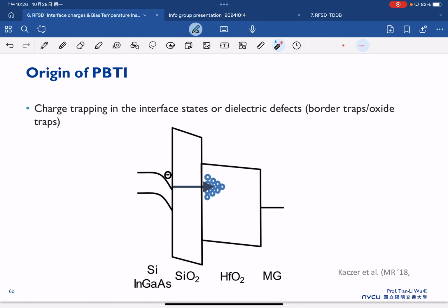So here, we talk about some more recent understanding of the origin of the PBTI. In the past, we were always thinking that the interface state is the issue. That's the interface state. So that's the understanding from 20 or 30 years ago. But of course, as you know, the technology changes all the time, which means our understanding should change all the time as well. After a certain moment, the interface cannot fully explain what we have already seen in the degradation. So that's why we started to propose that these electrons not only can be trapped